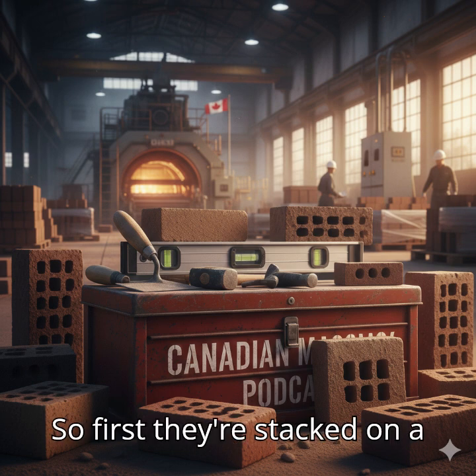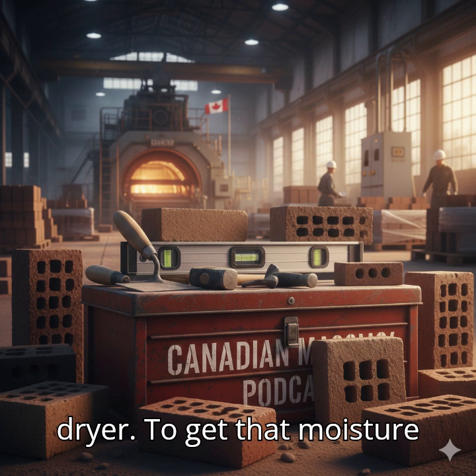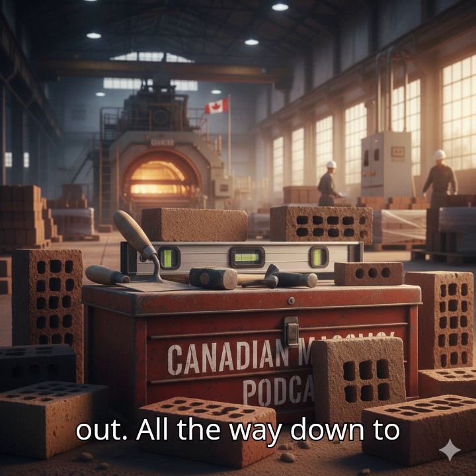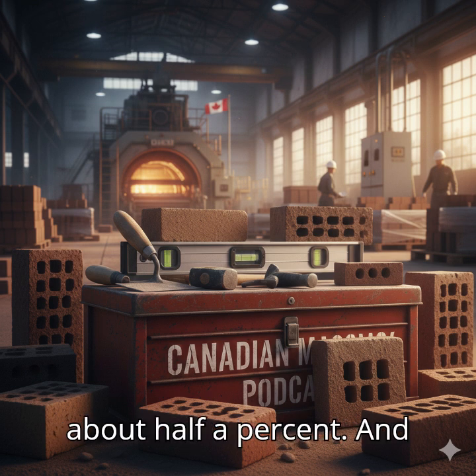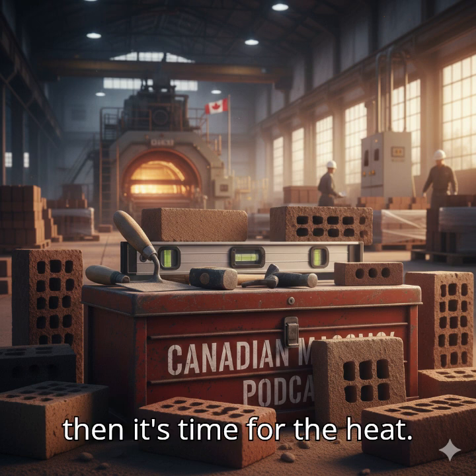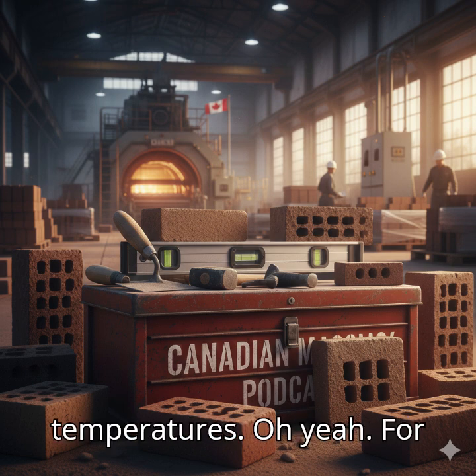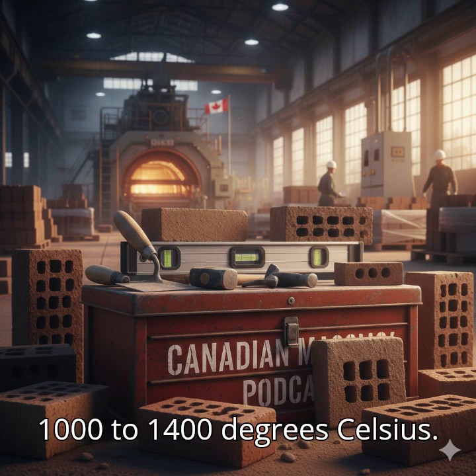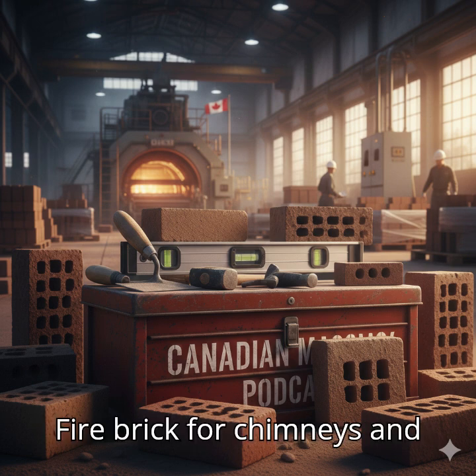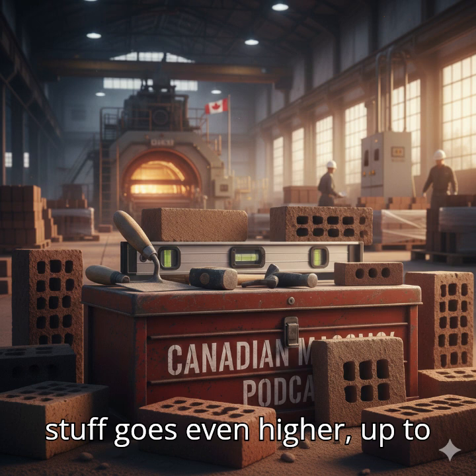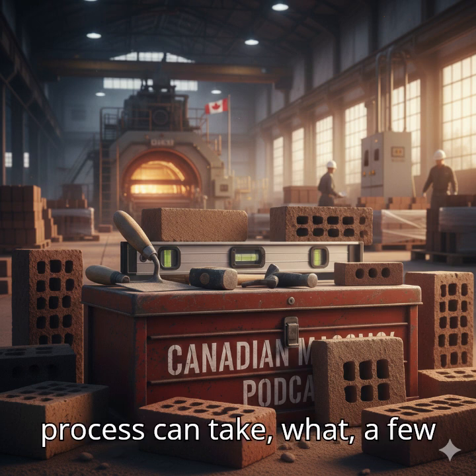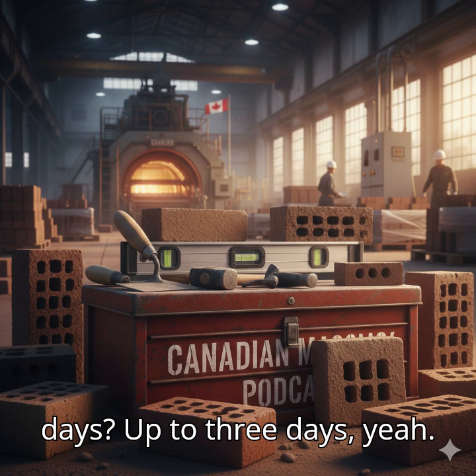So first, they're stacked on a kiln car and they go into a dryer. To get that moisture out. All the way down to about 0.5%. And then it's time for the heat. We're talking serious temperatures, right? Oh, yeah. For face units, you're looking at 1,000 to 1,400 degrees Celsius. Fire brick for chimneys and stuff goes even higher, up to 1,550. And the whole firing process can take, what, a few days? Up to 3 days, yeah.